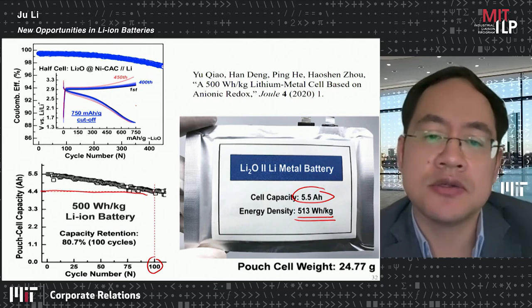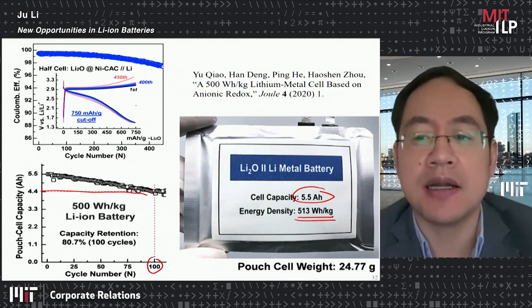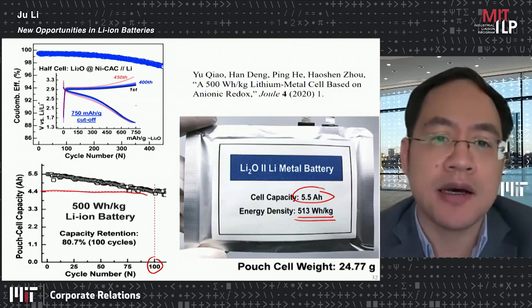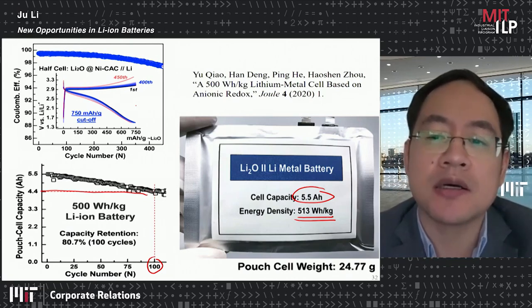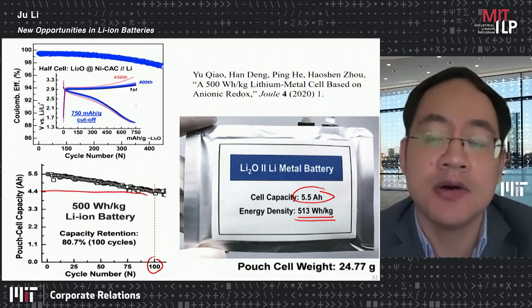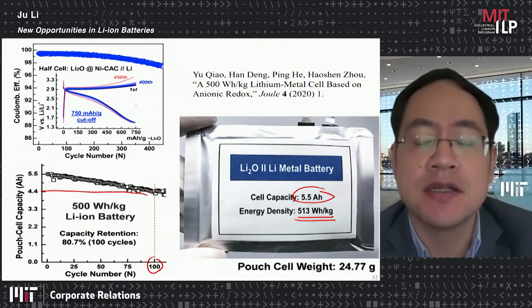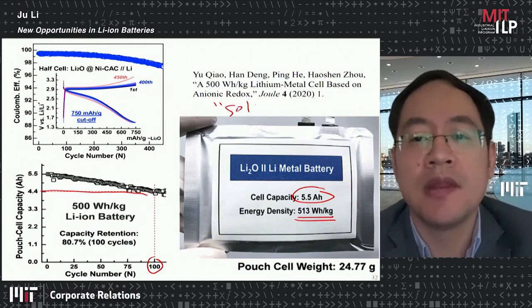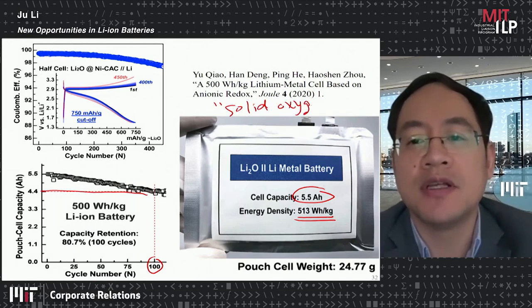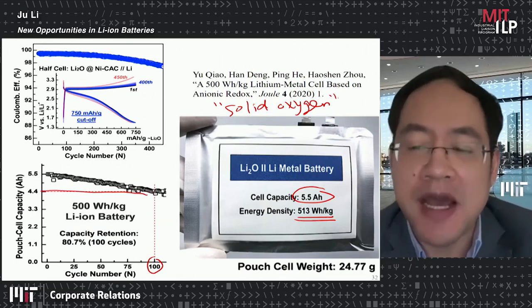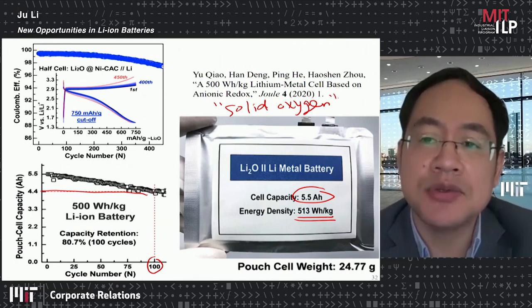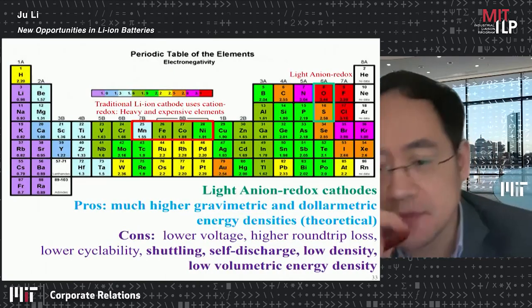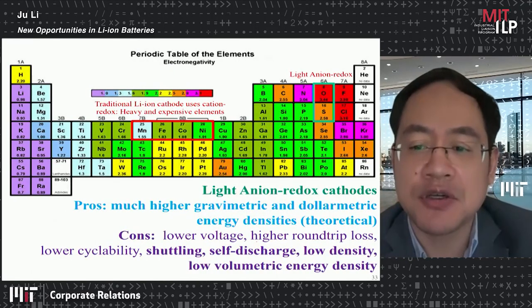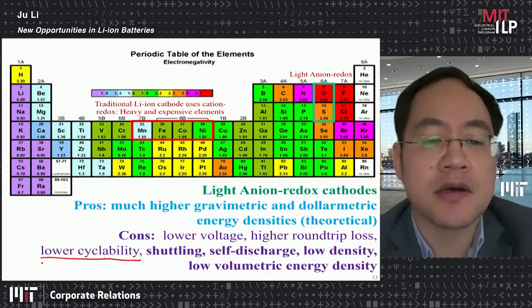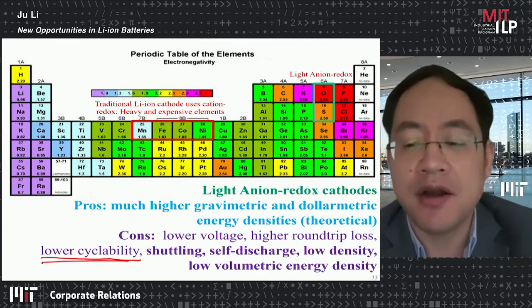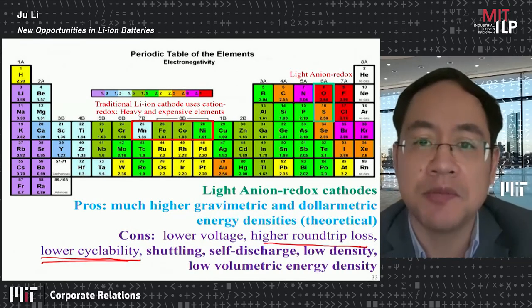So this is a pure anion redox. Basically, the goal is to have essentially a sealed lithium oxygen battery and avoid O2, but going to peroxide and superoxide and cycle between these condensed phases. So this is what I call the solid oxygen strategy. It's just like a solid sulfur strategy. So this is trying to do the same thing to stabilize oxygen anion redox. So with that, Professor Zhou's group have shown you can have very good cyclability and reduce the round trip loss.